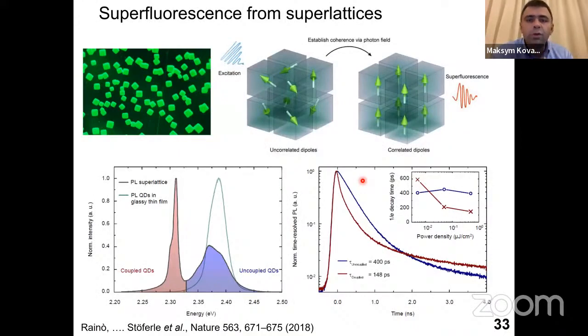Now, when you cool to low temperature, what was super exciting about 5 years ago, when our colleagues observed these sharp emission bands at lower energies than your normal excitonic band, which suggests some coupling. And this is a coupling, a coherent coupling of these entities.